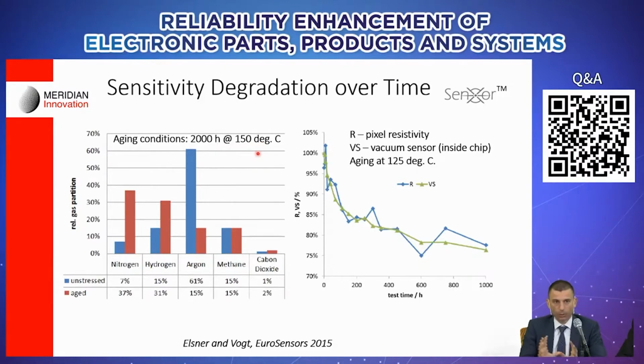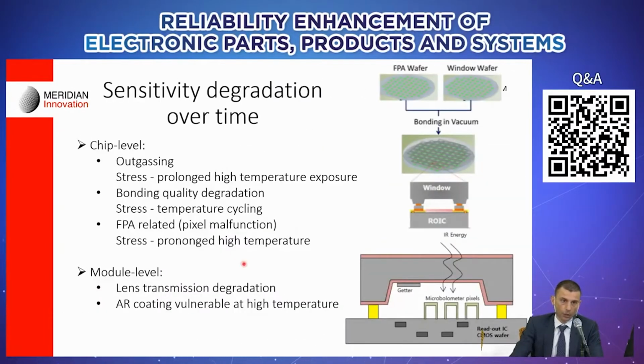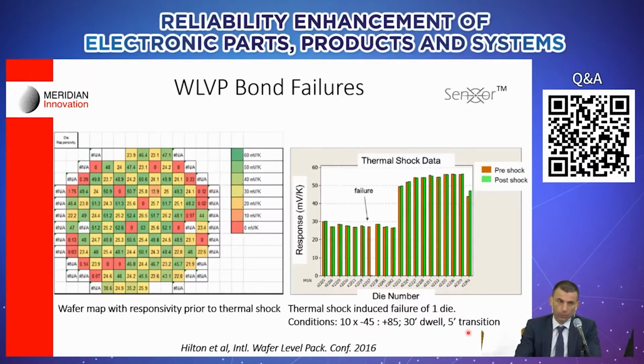Note that these two problems, the bond strength and the sensitivity degradation, are tested in a different way. For the bond strength, it was the sudden change in temperature that may trigger bond rupture by means of some kind of delamination, because you typically have different layers of materials that may have different thermal expansion coefficients. So this is the physical mechanism that you're driving, that you're accelerating and trying to stress. Whereas in the case of sensitivity, you're simply trying to accelerate the release of these gas molecules that I mentioned here that are trapped. You're trying to accelerate their release so that it happens ideally before you ship the product out.